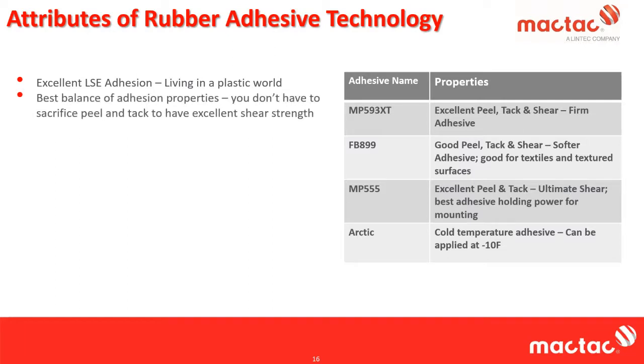We also at MacTac believe that rubber-based adhesives give you the best balance of adhesion properties. What we find is that you don't have to sacrifice peel and tack to also have excellent shear strength. Oftentimes in an acrylic product, you have a trade-off between something that's highly cross-linked and exhibits high shear strength, but you may see lower peel and tack numbers, and that's just some of the basics of the polymer design itself. And rubber-based adhesives typically are the most economical solution for many applications.